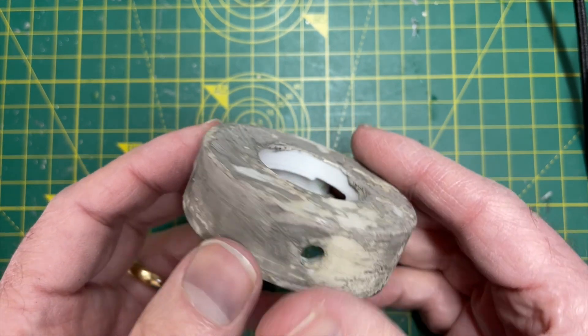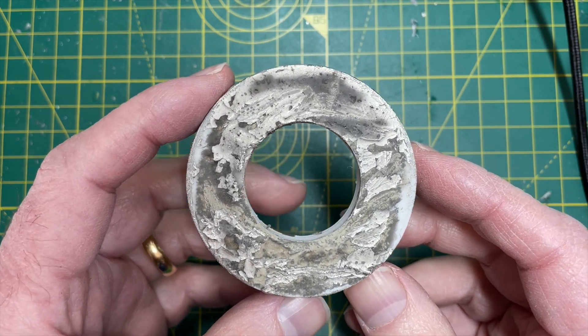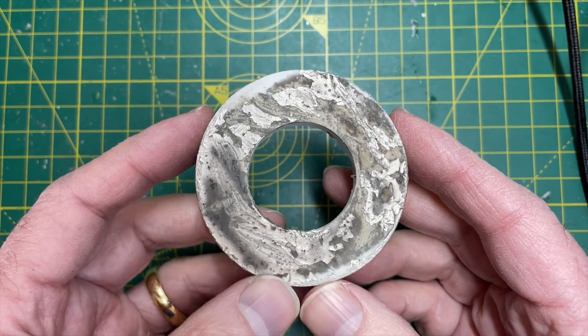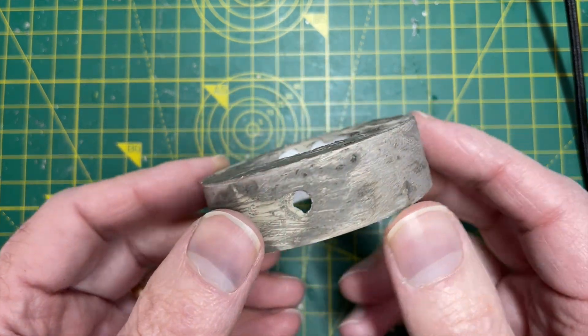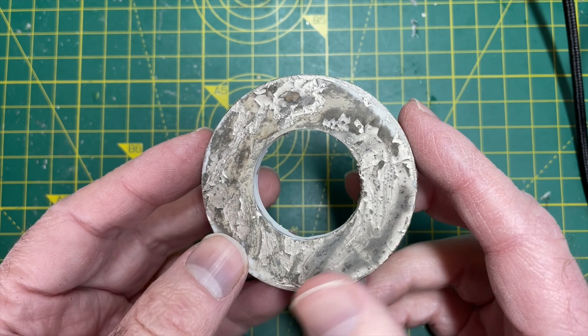This one — not so good, but unsurprising. This next one had a slightly better coating of the conductive paint and we have got some nickel plating. I think the current on this might have been too high, so the nickel started flaking off, but it's got some plating.